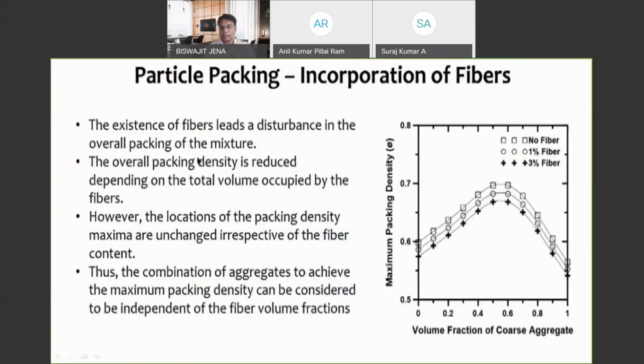Again, we have incorporated the fibers. These long fibers in this matrix of aggregates are going to displace some of the aggregates, and you are going to have a lower packing anytime you put in something of a different aspect ratio. You will see in this picture that the maximum packing density is reduced a little with the addition of fibers. But the advantage is that the fibers give so much in terms of ductility, so you can increase the ductility of the ultra high performance concrete.